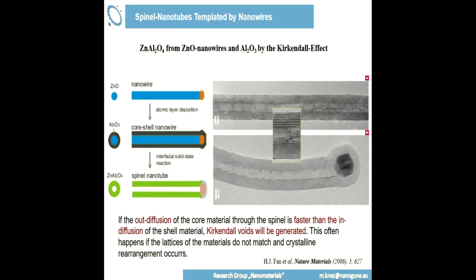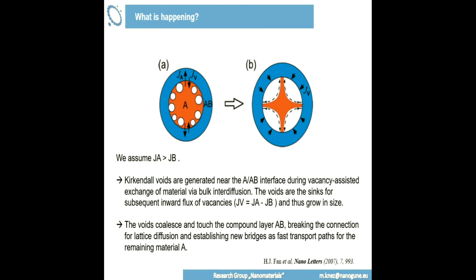And those voids happen because, this is another example. So this is one of our works where we did a zinc oxide nanowire and coating with aluminum oxide. And then we have this non-equilibrated diffusion, zinc oxide diffused to the aluminum oxide, producing a spinel, and left a void, a pore behind. So we had a nanotube. But what is happening here? The point is you have a much faster diffusion from one material into the other than the opposite.